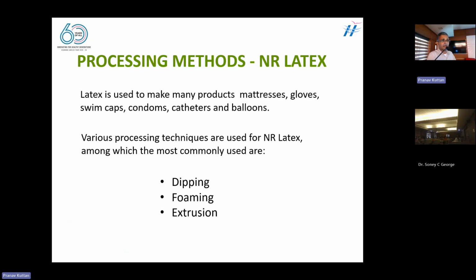Then extrusion. The threads which are used in your garments, which are all elastic threads, are formed by the process of extrusion. The latex from the mold is pushed through a spinneret of small diameter, of whichever size you like. This is put into the heating solution for getting cured. You will get a thread which has strength and elasticity, which is used in our garments.